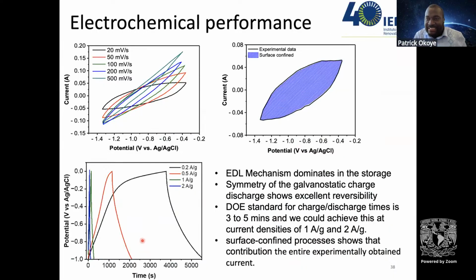And the discharge time set according to the DOE is between 3 to 5 minutes. But we saw that we could also achieve these 3 to 5 minutes at current densities of 1 and 2. So when we tested the surface area or the surface-confined processes, we found that the surface-confined processes account for the entire experimentally obtained currents. And then we knew that we are on the